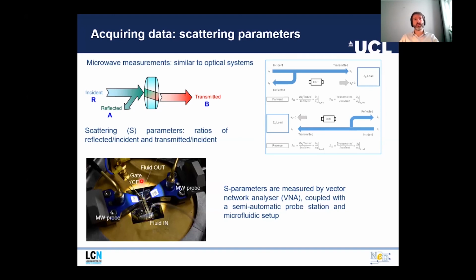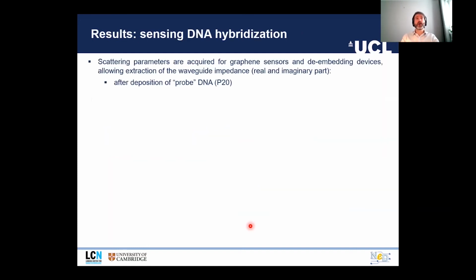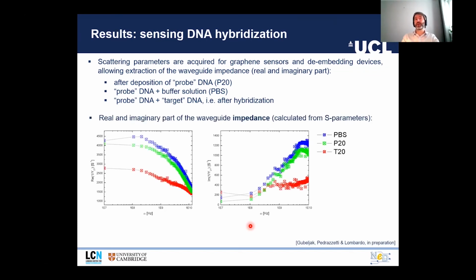So here we have the array, we have the gate, which I would more correctly call the counter electrode. That's the microfluidic in and out, and these are the two RF probes. And basically we are acquiring the scattering parameters at different stages: after the deposition of the probe, after the deposition of the probe in the presence of the buffer solution, and finally having probe and target DNA, which means the sequence we want to identify. We can measure the real and imaginary part of the waveguide impedance. So we can see that there are quite significant changes the moment we introduce the target sequence. So we have a change in the real as well as the imaginary part.